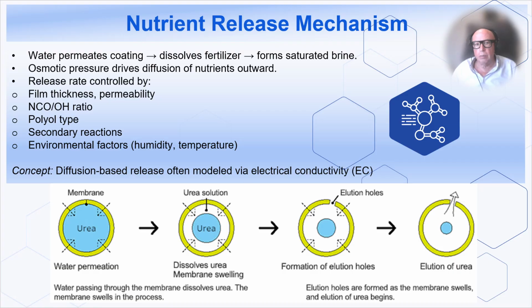Nutrient release mechanism. CRFs stand out for their consistent diffusion-driven release. Water permeates the coating, dissolves the fertilizer salts, and forms a saturated brine inside. Osmotic pressure then drives nutrient diffusion outwards through the polymer film. The release rate is controlled by film thickness, permeability, NCO to OH ratio, polyol type, secondary reactions, and environmental factors like humidity and temperature. But the key difference from CS systems is that this process is predictable and modelable.